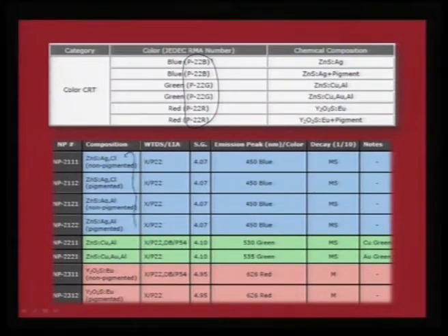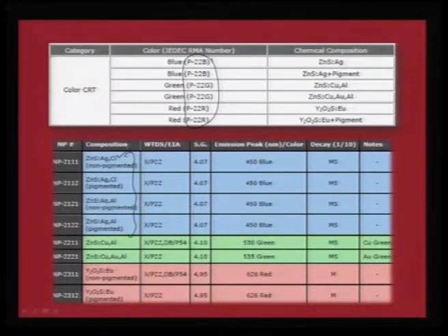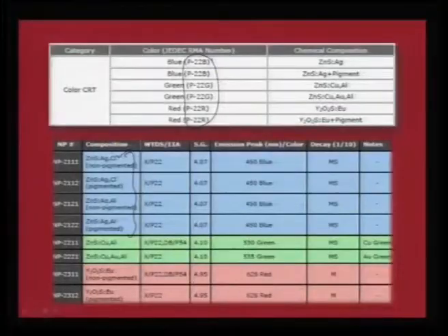As you would see here, in all these blue emitting phosphors, it is silver, but along with silver you also see a chloride ion that is doped, which is considered to be a coactivator. So, if you want a very strong fluorescence, not only do you dope with silver, which is the actual dopant and the activator, you also use chloride as a coactivator, which improves the efficiency of these compounds.